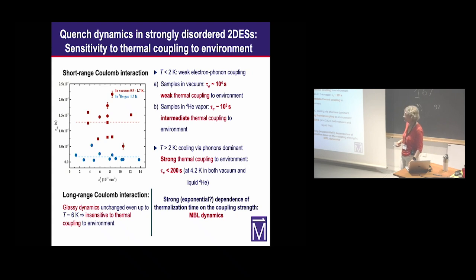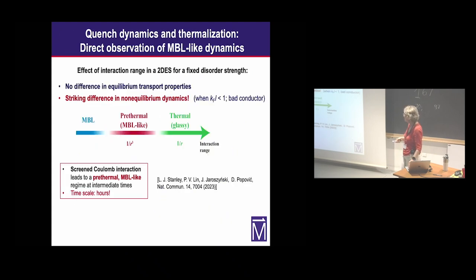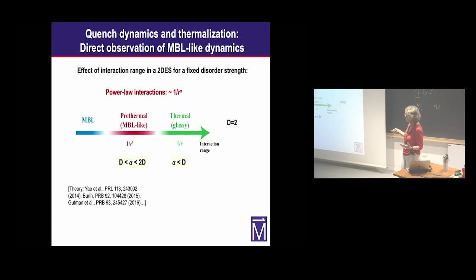Okay, so the conclusions are here. There is obviously a strong effect of the change in interaction range. In the long range, the dynamics is thermal, although glassy. And in the case of a dipolar interaction, it's consistent with MBL. This is actually the situation that was under debate theoretically. So the result seems to support those who argue that true MBL cannot exist in this regime.